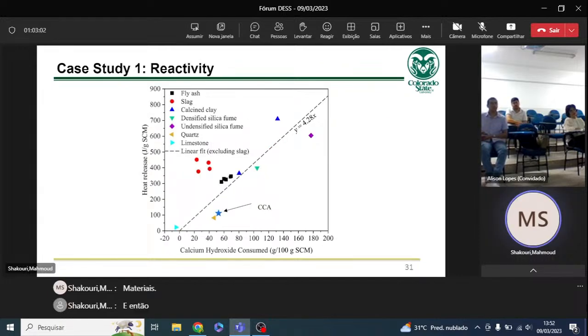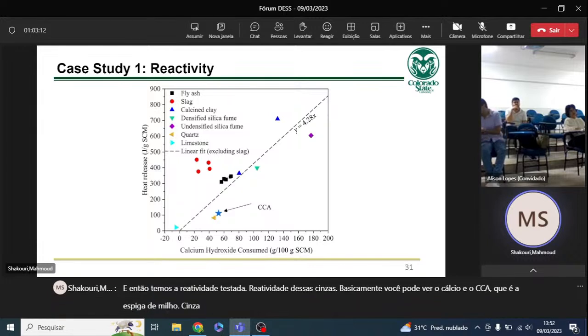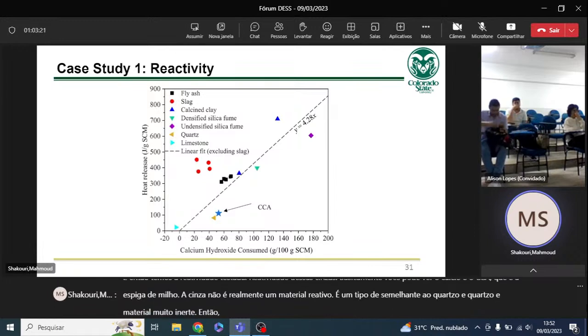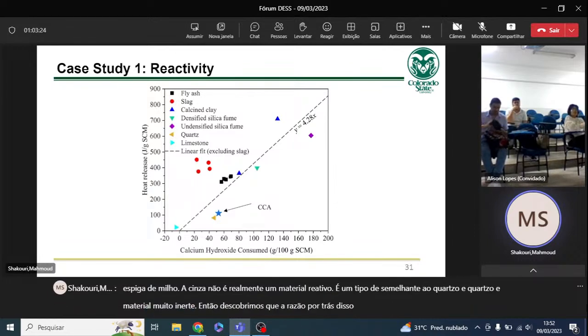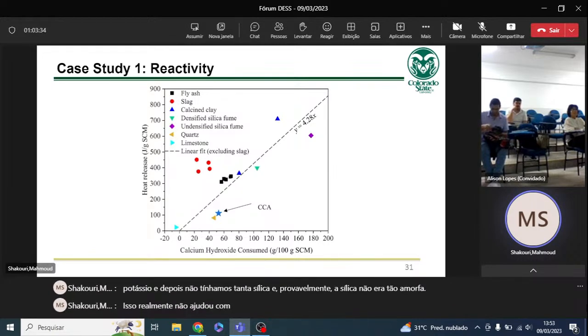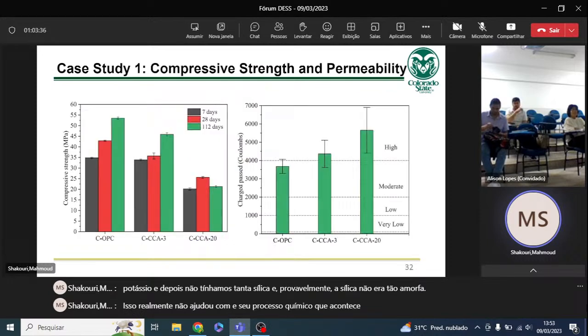And then we tested the reactivity of these ashes. Basically, you can see the CCA, which is the corn cob ash, is not really a reactive material. It's similar to quartz, a very inert material. So we found out the reason behind that was that first of all, we had too much potassium, and then we didn't have that much silica, and probably the silica was not that amorphous. So that really disrupted the chemical process that happens during your hydration.